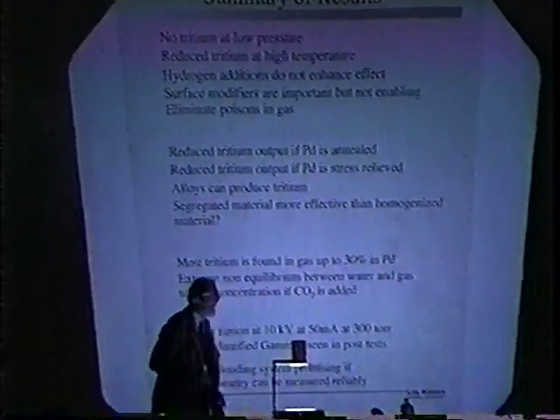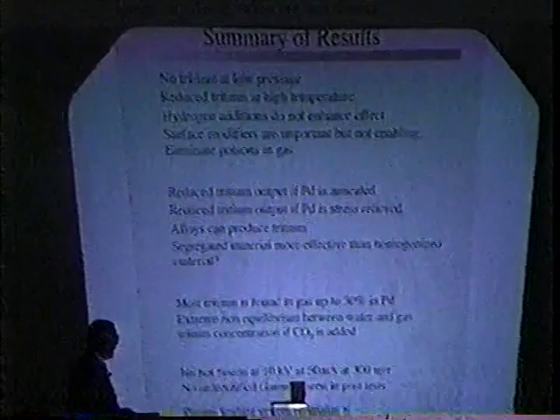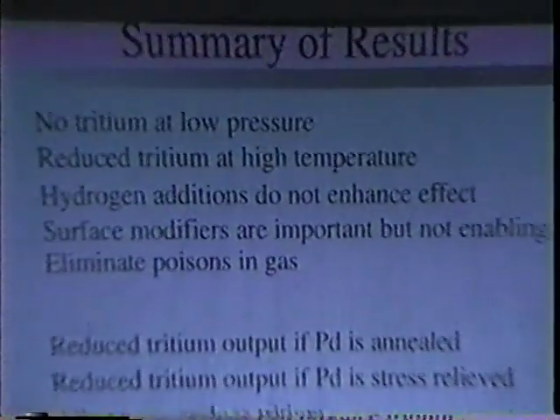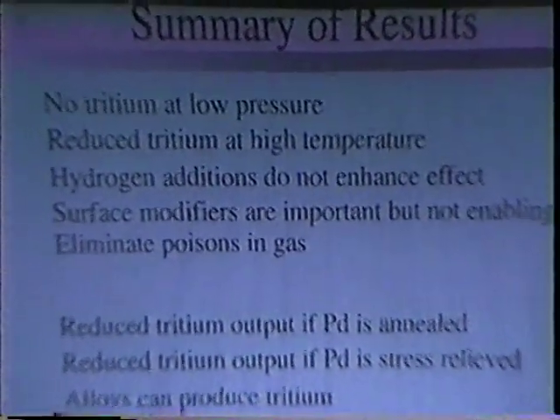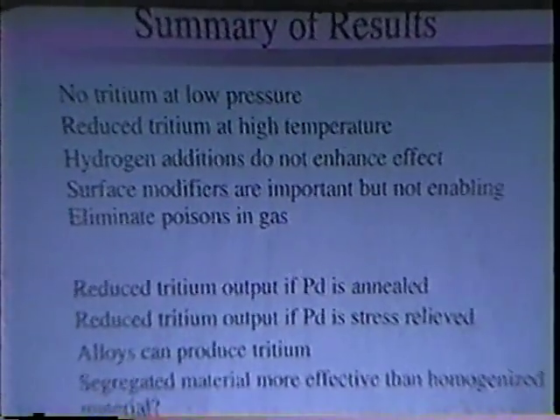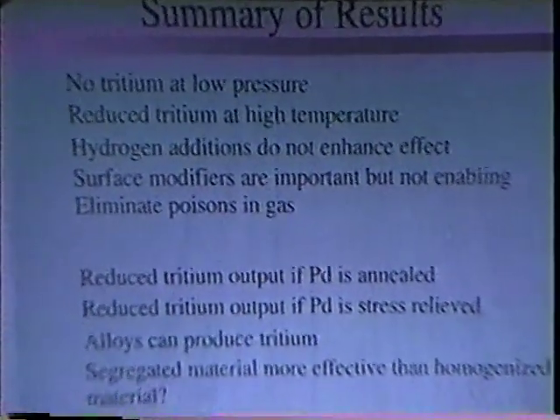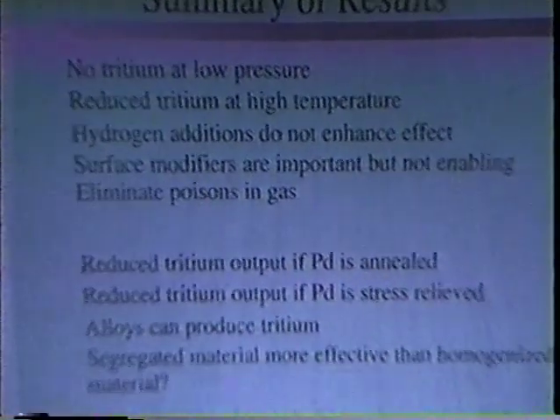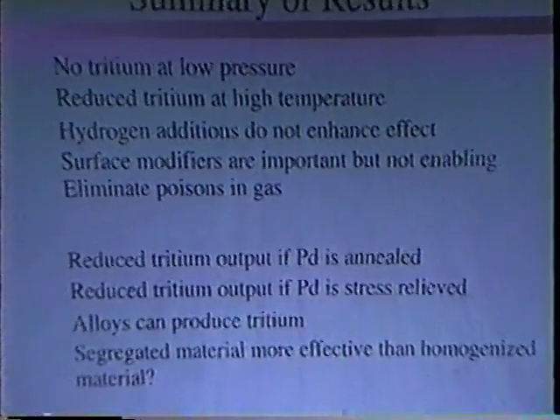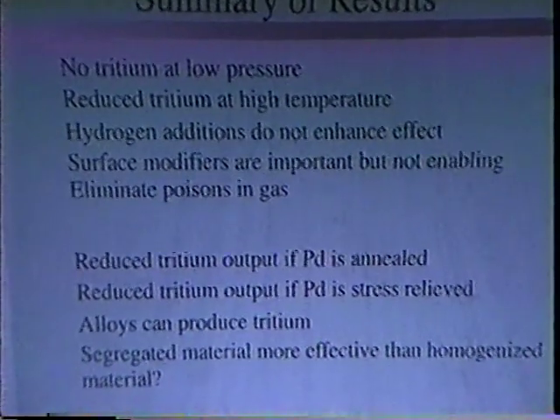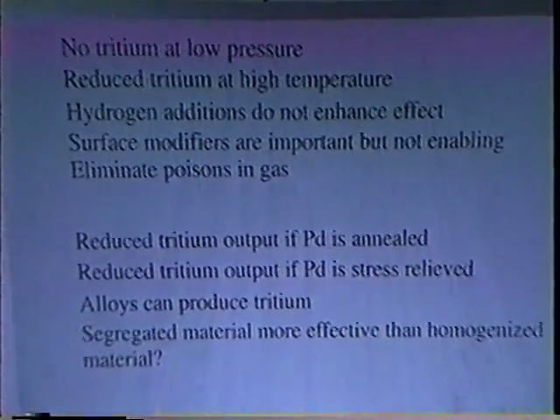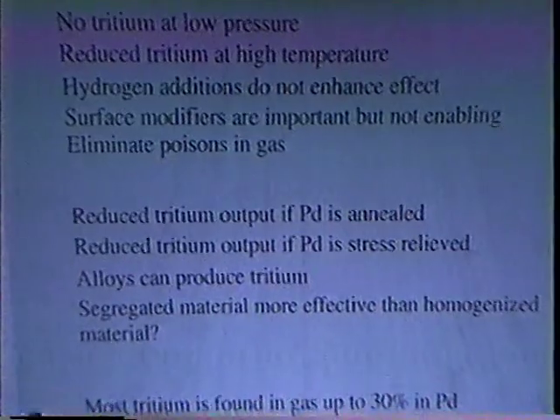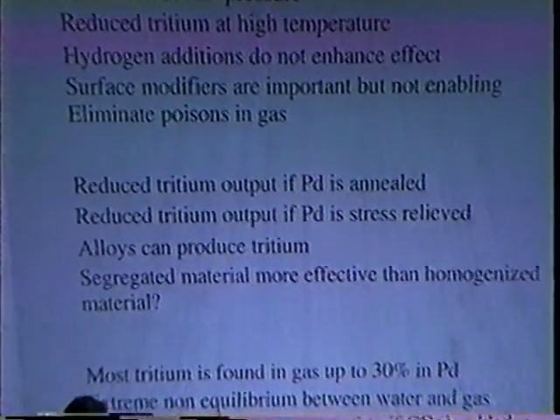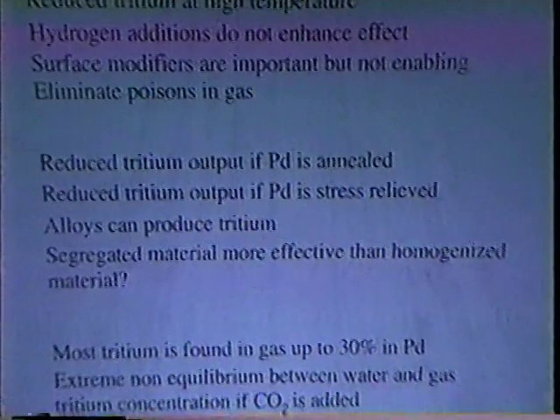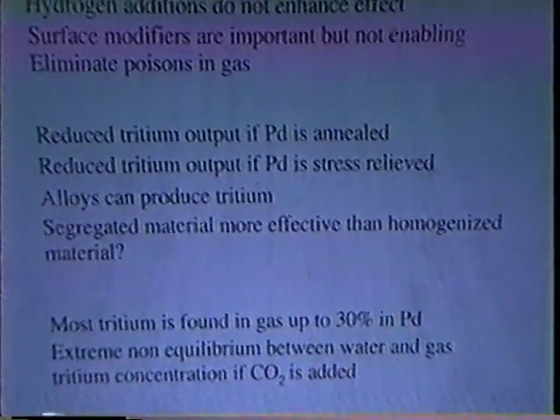Okay, the conclusions. Summary of results. There's no tritium produced at low pressures. You have to be above a certain composition within the palladium for tritium to be produced. You get reduced tritium at high temperatures, and that's undoubtedly because at high temperatures the palladium is deloading. Hydrogen additions do not enhance the effect, so we're not looking at the alleged helium-3 production or some other kind of reaction involving both deuterium and hydrogen.